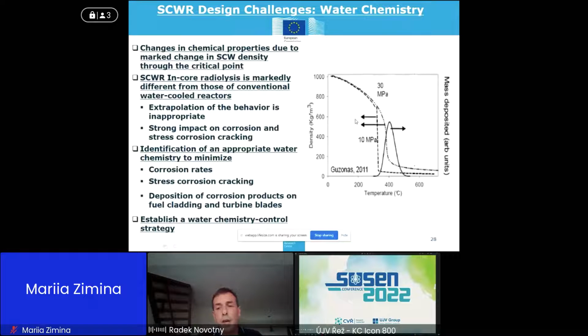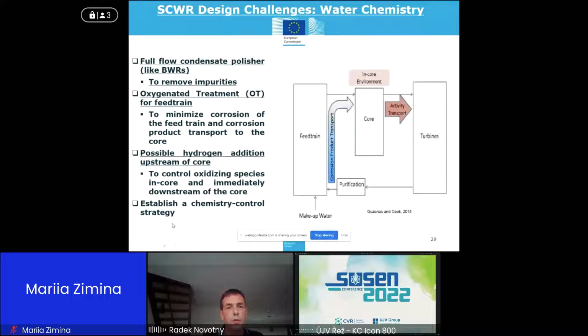And based on the results of radiolysis, we will see how strong an effect it will have on corrosion and stress corrosion cracking. And of course, it can be reflected in follow-up testing if we see some big changes, for example, in the concentration of oxygen that we could expect. And of course, we need to establish a water chemistry control strategy. In this case, we can use the experience from current light water reactors or supercritical boilers, and it should help us simplify the whole process. And here the experience is really huge.